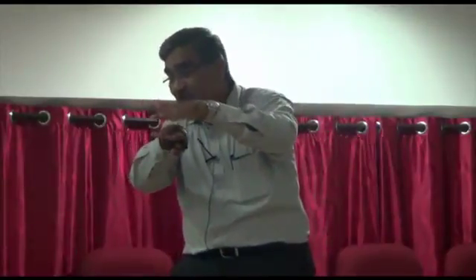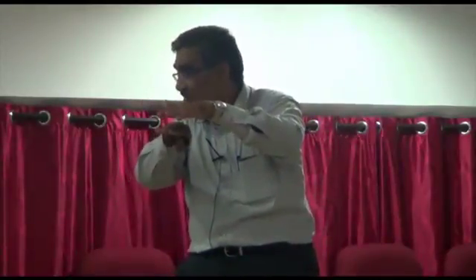And we also know why this happens, again because of the electron confinement. As I told you in the particle in the box, the layers were very close by, so they would interact with each other. Now I have separated the layers by making it narrow at the tip of these walls. So at the tip of the walls, the electrons travel without any electron interaction. That is how we can get long coherence spins.